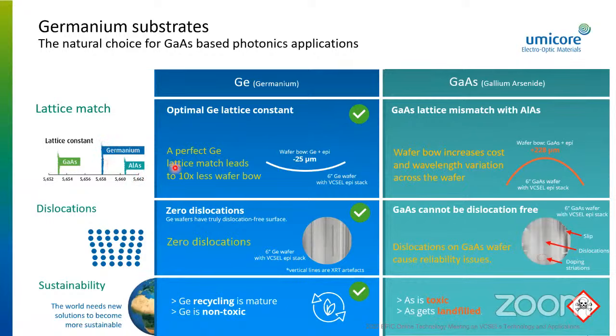So because of that, when you start to grow your heterostructure, gallium arsenide, aluminum arsenide, if you do it on germanium, you're almost stress neutral. And in combination with the high strength of germanium as a material, you get much less bow. So actually, it's about an order of magnitude less. And this is a comparison performed by IQE on 6-inch germanium wafer and 6-inch gallium arsenide wafer with the same VCSEL stack. So then in terms of dislocations, germanium is an elementary semiconductor.